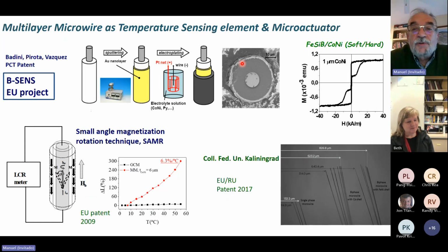Another application: within a European project, we were able to fabricate a magnetic wire, starting with a glass-coated microwire. We sputtered a tiny gold nanolayer, and then by electrodeposition, we electroplated an external shell. So this is a cross-section of the microwire. You see the amorphous core, the pyrex in the middle, and the external shell. So we can tailor the behavior of the two magnetic phases. And this is, for example, the typical signal for a soft-hard bimagnetic microwire.